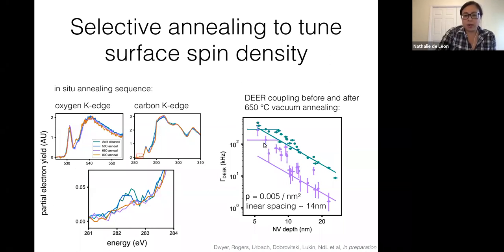So now this is nice because we have some handle to selectively anneal away the surface spins, and we think we have a nice signature that we can also look at in X-ray spectroscopy. So this is around where we had gotten to right before quarantine. And we were dealing with a few big puzzles in the data at the time.